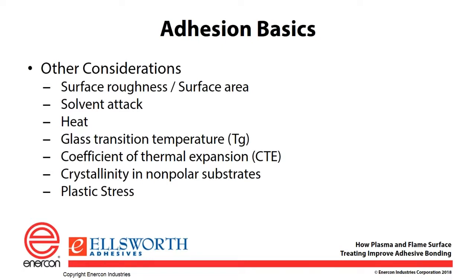Coefficient of thermal expansion is an important concept, particularly when dealing with the bonding of two substrates that are different from one another. An example of this would be if you're bonding a metal to plastic. The metal will have a low coefficient of thermal expansion, whereas the plastic will have a significantly higher value. In real-world use, with temperature fluctuations, these differences in coefficient of thermal expansion can cause the materials to delaminate from one another. To avoid this, it's very common to use materials that aren't quite as hard and are a little more flexible to accommodate these differences.